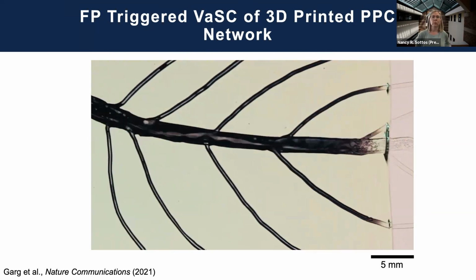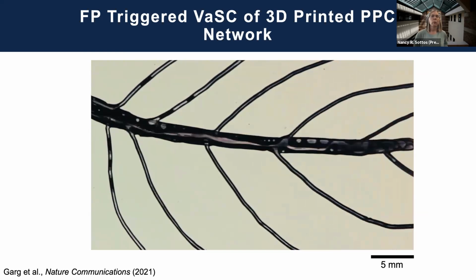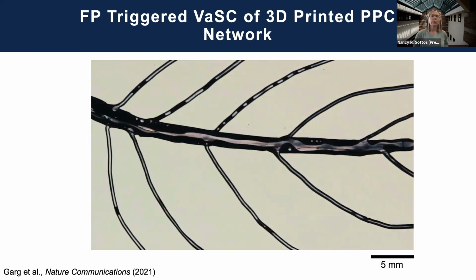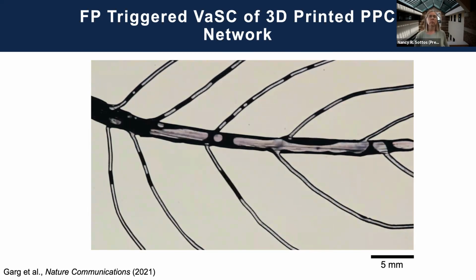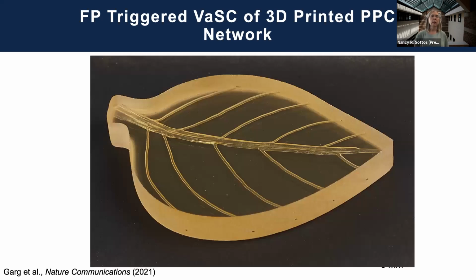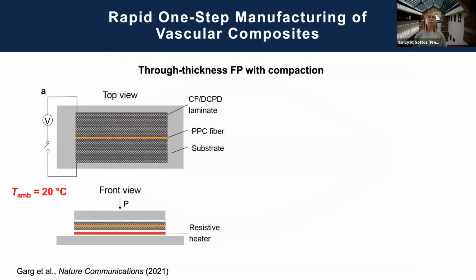And it's just a fun video to watch. And what we are left with after this is evacuated out, and usually we just rinse the channels a little bit to get rid of any residual monomer, is our leaf-like structure that we're able to create quite rapidly without the use of a high-temperature oven. And this work just appeared 2 weeks ago in Nature Communications, and so there's a lot of details of the process in that.